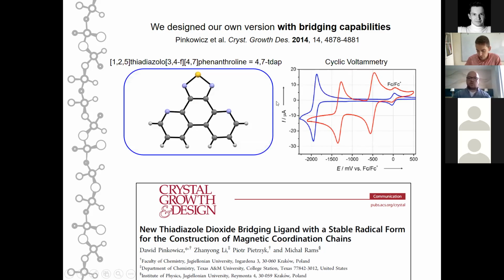And just to give you some comparison on why dioxothiadiazoles are so much better in terms of electrochemistry than thiadiazoles, here is a cyclic voltammogram for the thiadiazole, the blue trace. You can see that it can be reduced to a stable radical as well, but this radical will be extremely sensitive to oxygen, even traces of oxygen, because the reduction occurs at very low potential versus the ferrocene couple.